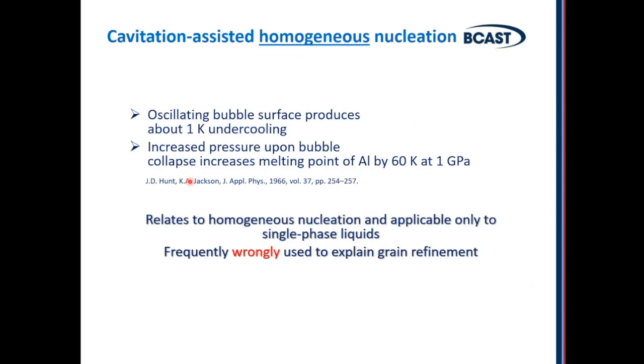One of the major applications of ultrasonic melt processing, as applicable to liquid metals and specifically to aluminium, is nucleation. So we want to refine the structure of solid metal by assisting nucleation of solid phases during solidification. And of course, it starts from nucleation. The more nuclei you have, the finer the structure. So there are a number of hypotheses and theories on how cavitation can assist nucleation.